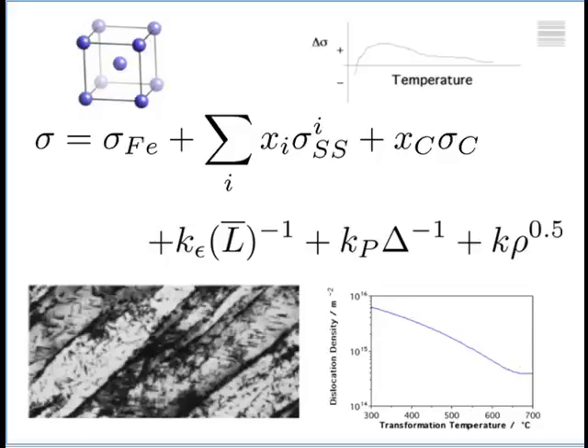So every single steel will have a certain amount of strength which comes simply from the crystal structure. And that strength increases as we go down in temperature. And this is one of the reasons why steel becomes brittle at low temperatures, because as it gets stronger, it becomes difficult to deform it, and therefore you cannot absorb energy during fracture.